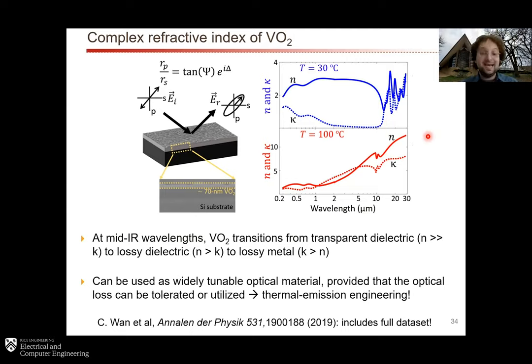And so this can be used as a widely tunable optical material, provided that you can tolerate the loss in the metallic state and the intermediate state. And of course, that's totally okay for thermal emission engineering. And so this is something that we have been using a lot.